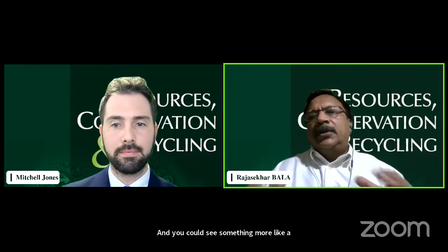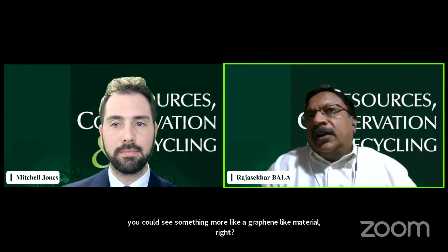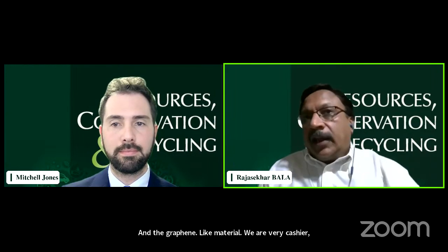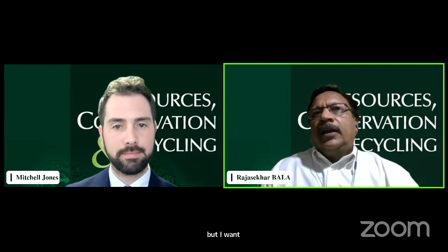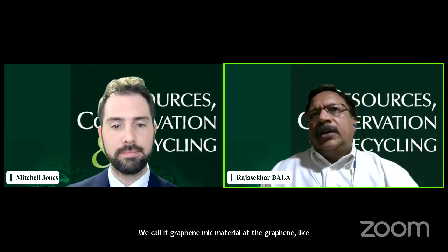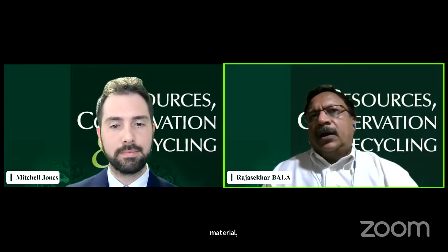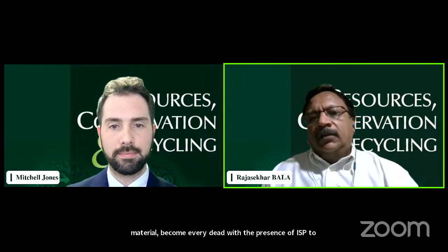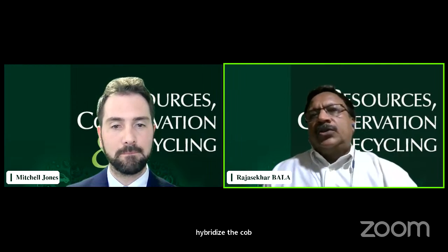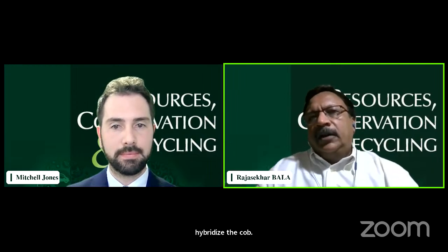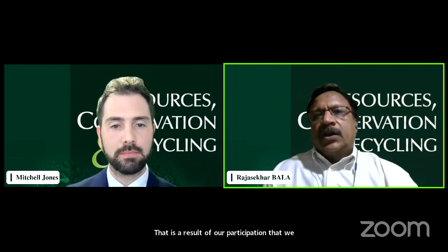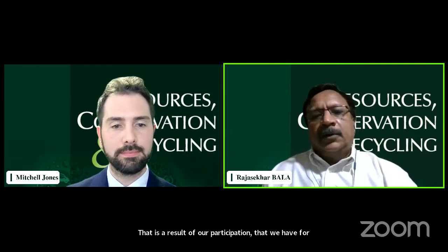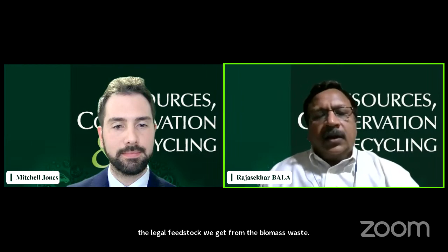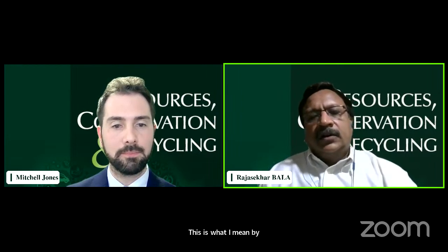And the graphene-like material, we are very cautious. We don't want to call it graphene. We call it graphene-like material. The graphene-like material becomes evident with the presence of sp2 hybridized carbon. And that is the result of aromatization that we have from the lignin feedstock we get from the biomass waste. This is what I mean by graphitization.